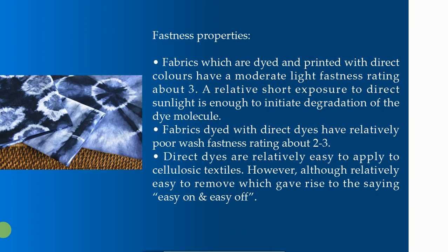Fastness properties. Fabrics which are dyed and printed with direct colors have a moderate light fastness rating of about 3. A relatively short exposure to direct sunlight is enough to initiate degradation of the dye molecule. Fabrics dyed with direct dyes have a relatively poor wash fastness rating of about 2-3. Direct dyes are relatively easy to apply to cellulosic textiles. However, they are also relatively easy to remove, which gave rise to the saying, easy on and easy off.